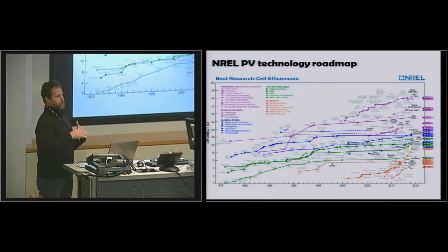So in order to absorb all the light, silicon has to be relatively thick. This is one of the challenges with silicon: you have to have fairly thick layers, 50 microns thick, to absorb all of the light. That means your solar panels can be relatively heavy, and you're going to have to use a lot of silicon. People have been working on thin film silicon, but inherently you're fighting nature with those.